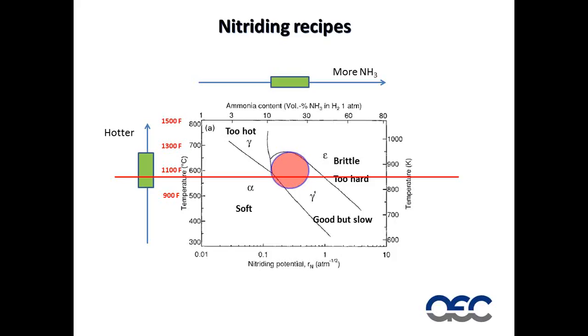So really, this lower part here, if I can get my mouse to appear on the screen, here we go. This lower part here is an ideal area for us to operate in. This gives us the good nitriding layer. It does not give us the white layer, and it does it at optimum nitriding speeds.